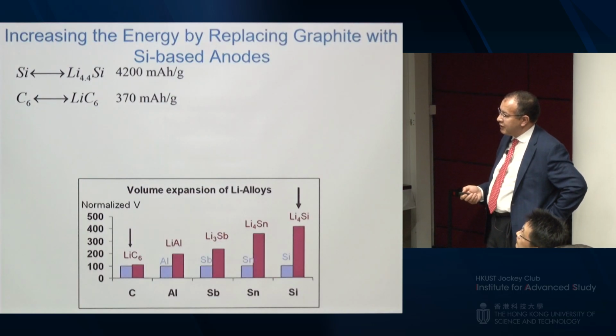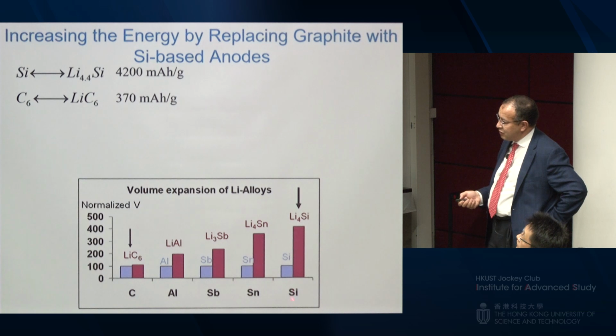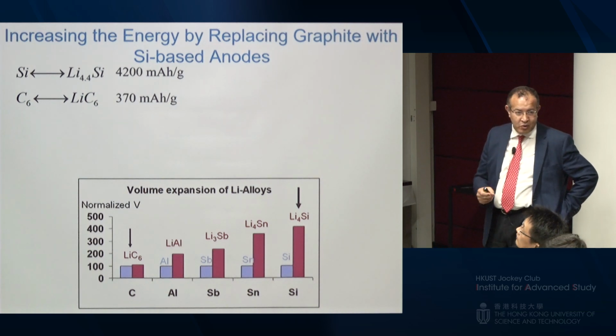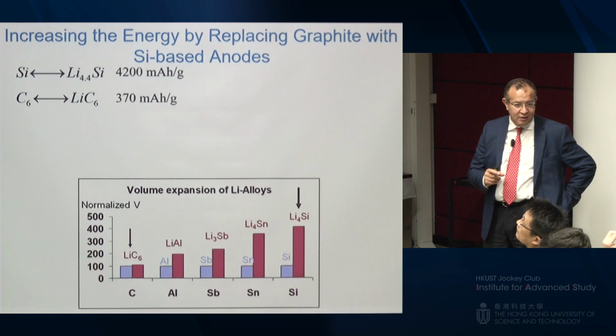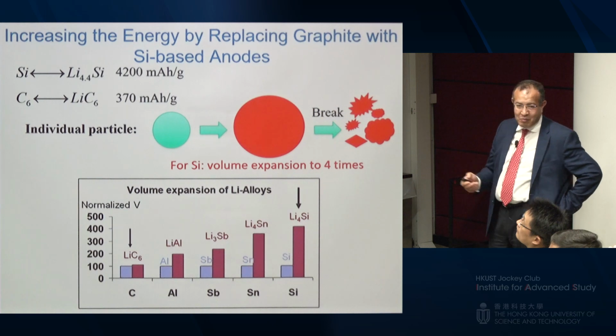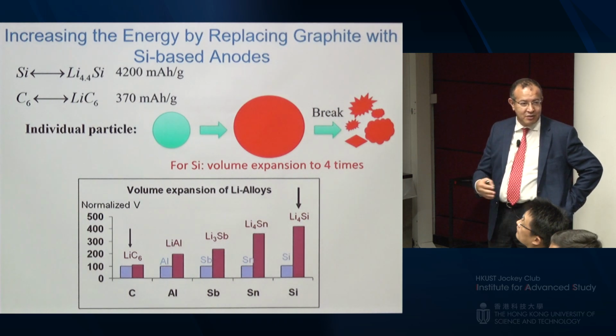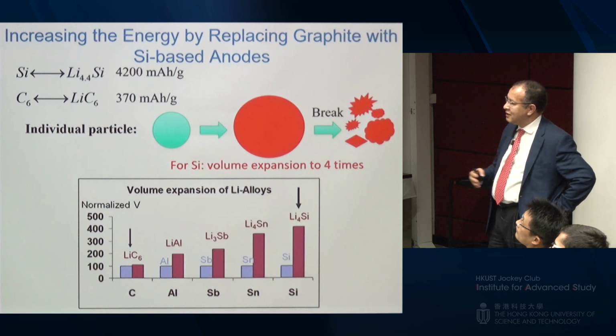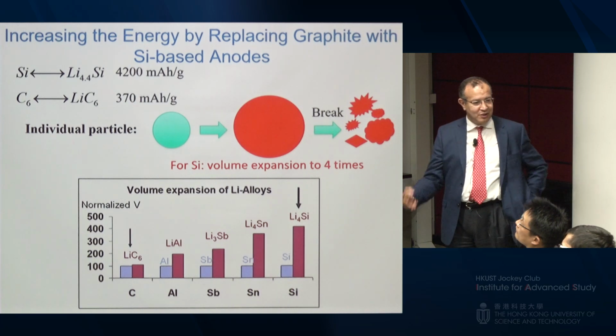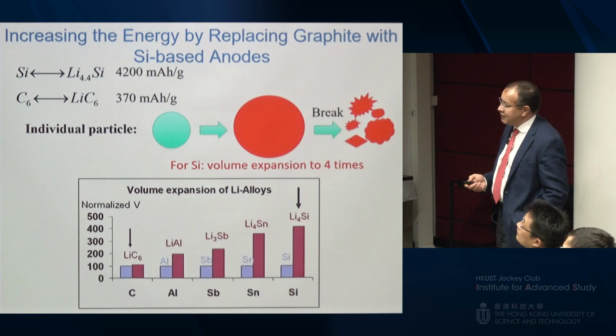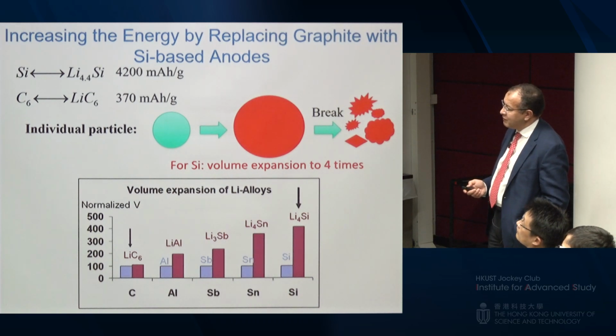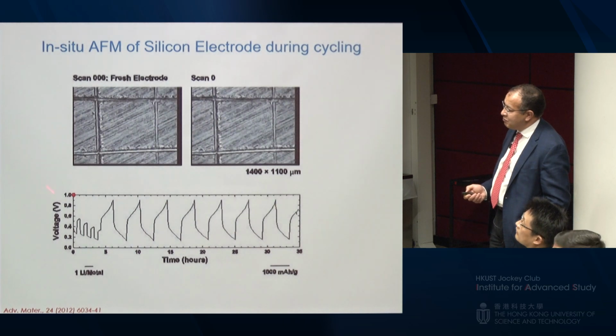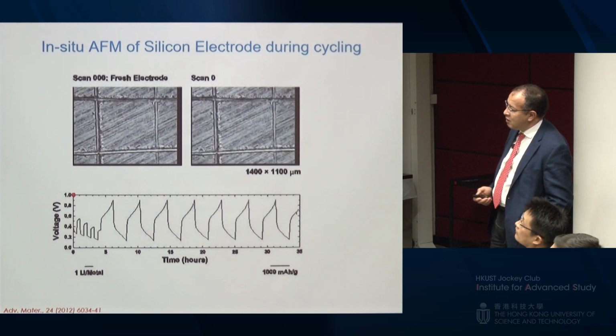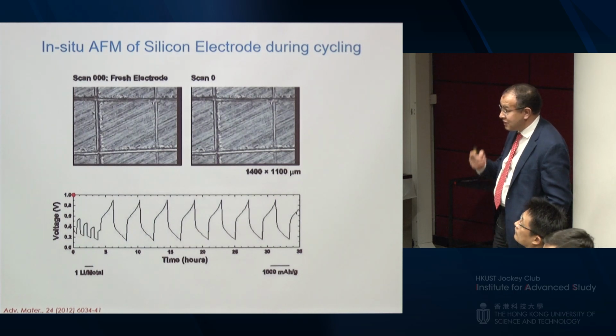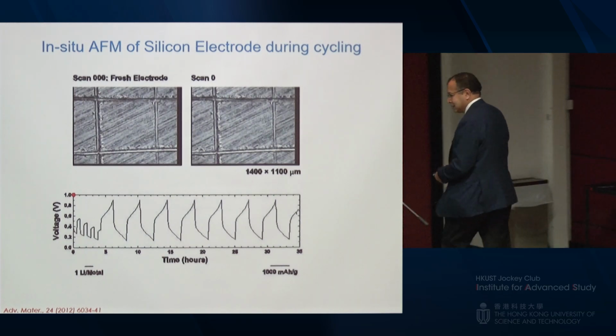Unfortunately, when you do the alloying, you get a lot of capacity, but you have huge expansion, volume-wise, almost 400%. That's not good. If you have a big expansion, you expect, after cycling, cracking of the particles and isolation. So when you isolate your particle, you lose conductivity, and that particle is dead. So your capacity will drop very quickly. So that's the problem. I think I have a video that shows an in-situ AFM, where we basically cycle and look at the surface of the particle by AFM to see what is happening, see if it's going to work.